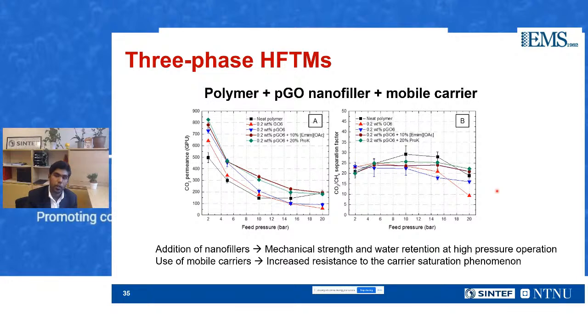Facilitated transport membranes, when you increase the pressure on the feed side with respect to CO2 partial pressure, then you saturate the carriers that is present in the polymer matrix eventually, after which the facilitated transport mechanism slows down. But when you use the mobile carriers, we see that the resistance to this carrier saturation phenomena is much higher in these mobile carrier systems than the systems which are not using mobile carriers.